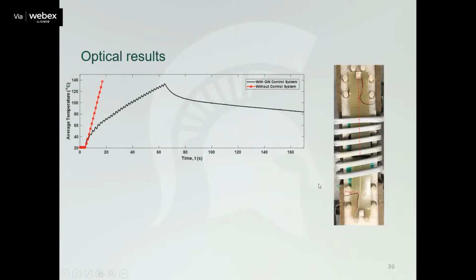So look at the optical results. You compare with the guided wave control system and without the guided wave control system. Remember that you measure the guided wave signals, then you can use that to control your induction heating into the adhesive region. Without the control, you'll see the temperature go up, skyrocketing very quickly. But with the guided wave control system, you have a better way of controlling the temperature in this adhesive region.